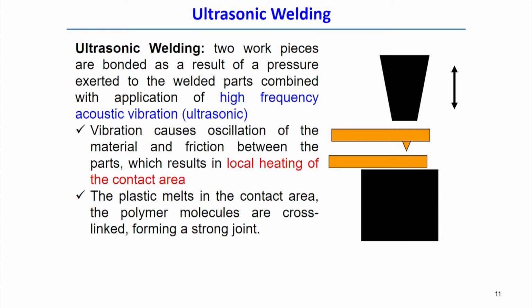High frequency acoustic vibration causes oscillation of the material, and the friction between the parts creates local heating of the contact area. This frictional heating occurs in a very small confined area. Therefore, the plastic melts in the contact area, and the polymer molecules are cross linked and finally form a strong joint. In the figure we can see the workpiece material, and this is the vibrating element creating the vibration; in the local area we generate the frictional heat, and then the parts can be joined.